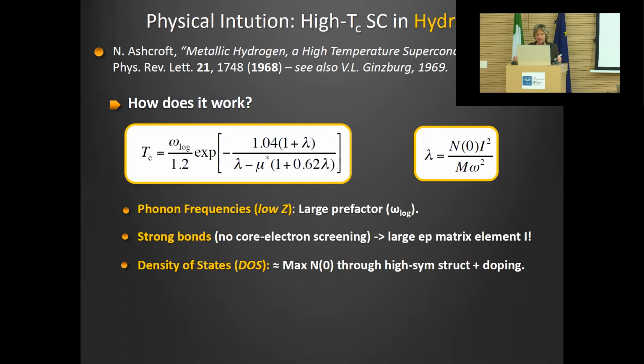The second factor actually appears in the exponent, this lambda, this electron-phonon coupling, and we can further divide it in two parts. The first part is N0, N of 0, which is the density of electronic states at the Fermi level. So this factor tells me that the more electrons are at the Fermi level, the more electrons are available for superconducting coupling, the higher the lambda, the higher the TC. Okay, this is simple. Why should atomic hydrogen have high N0?